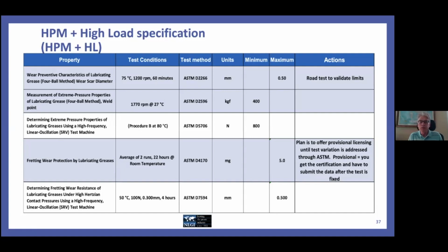And provisional licensing means you can certify your grease as HPM plus HL with no fretting wear data. The fretting wear data that you would provide would be unreliable anyway at this point in time. So this is one where you'll get provisional licensing, and then once ASTM has the test fixed, which I couldn't tell you when that will be, my guess is it's probably a year.